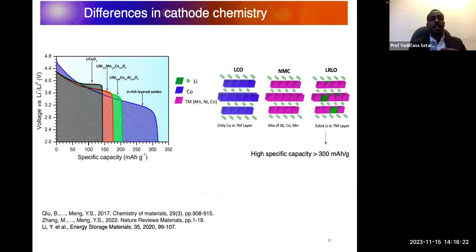Very recently, we have also seen new materials in addition to these oxides, manganese, silicate, borate, and the like. They call it lithium-rich layered oxide, the one in blue on the left side of the graph. The capacity is by far higher than the traditional metal oxides. How this happens is that they incorporate lithium oxide into the traditional ones and increase the lithium concentration, so that the capacity also increases at the same time.